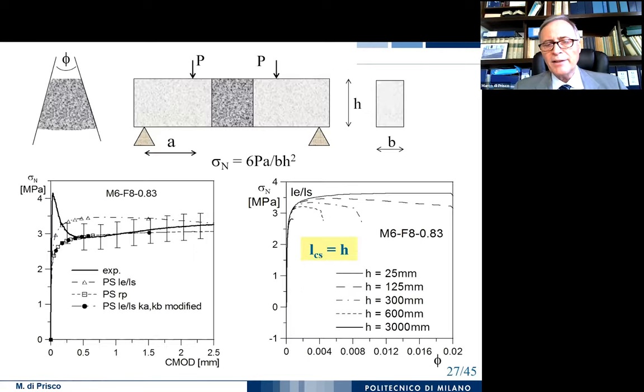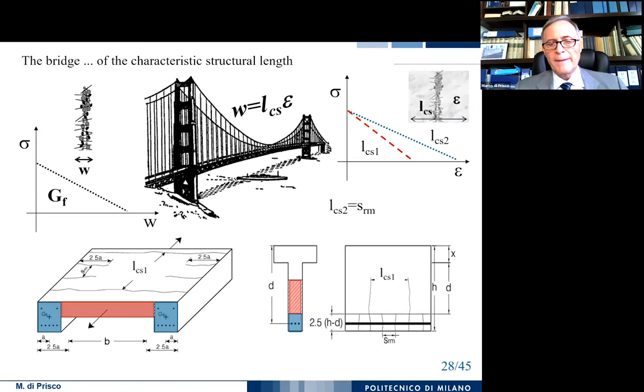And what is very important, we are able also, with the introduction of the characteristic structural length, to have a size effect behavior. So changing the depth of the beam with the same constitutive law, you have a final response which can be ductile for a very small beam and can be brittle for very deep beams.